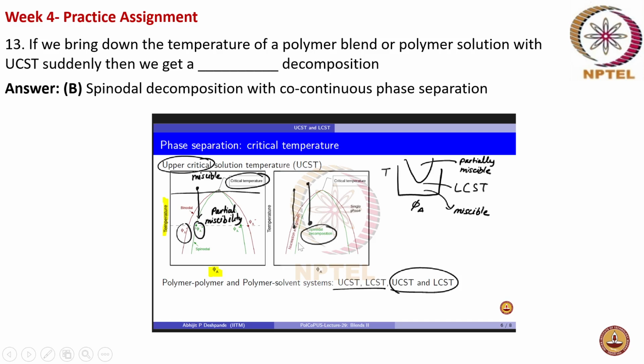whether it is lower critical solution or upper critical solution. One is spinodal and the other one is binodal. This green curve denotes the spinodal decomposition, and this one is binodal. If you bring down the solution's temperature suddenly, if there is a sudden drop, it gets into the spinodal decomposition zone. In this zone, the phase separation starts suddenly with a co-continuous phase separation. Whereas when the temperature is brought down slowly and it enters the regime of binodal decomposition, there will be nucleation and growth. So slowly the nucleus starts forming, the separation of the phases starts, and it develops.